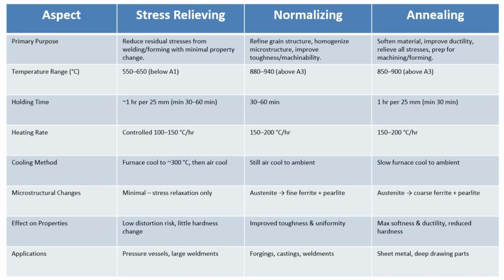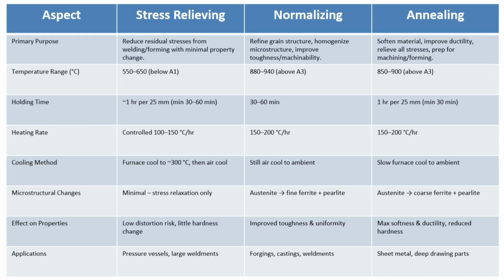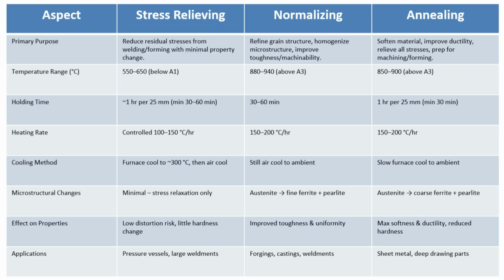Now, the effect on microstructure: minimal effect in stress relieving because it's not going into the phase transformation range, the lower transformation range, as I mentioned. But in normalizing, you form an austenitic structure and ferrite pearlite is formed. So this structure is also there in annealing. For the effect on the properties, very little change in hardness is expected. Basically, distortion is reduced. But in normalizing, improved toughness and uniformity, you will get more toughness. Charpy impact values will go up and you get maximum softness in annealing. So hardness will be considerably lower and ductility will be improved. Hardness is reduced, which is a very good property for the material.